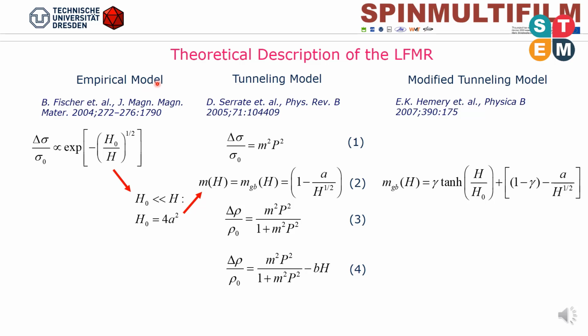The empirical exponential model is simply a good approximation of the experimental results, both for sintered and granular strontium ferromolybdate ceramic samples. The tunneling model, developed for barium strontium ferromolybdate, considers the conductivity due to elastic tunneling occurring through a barrier between two non-interacting grains, possessing equal spin polarization P but different magnetization directions in the neighboring grains, under an external magnetic field H. Since the average cosine of the angle between the magnetization directions of two neighboring grains yields the squared reduced magnetization m squared, the resulting magnetoconductivity equals m squared times P squared, equation 1.